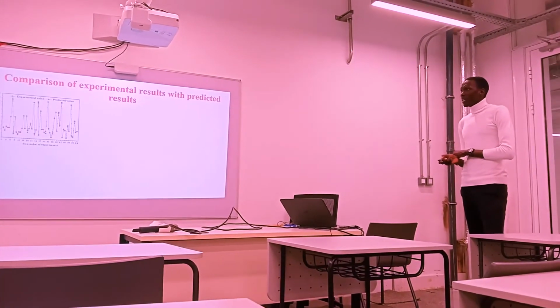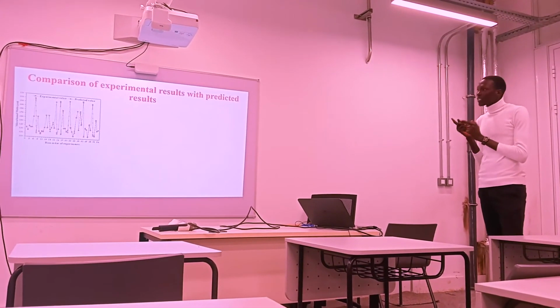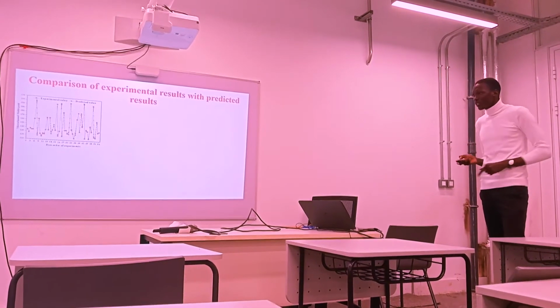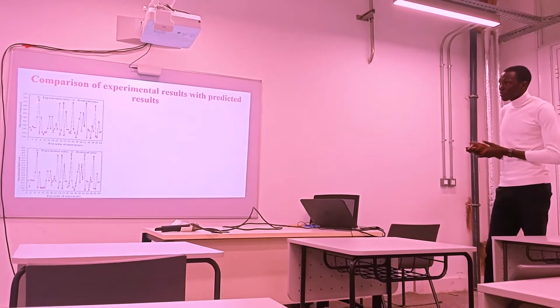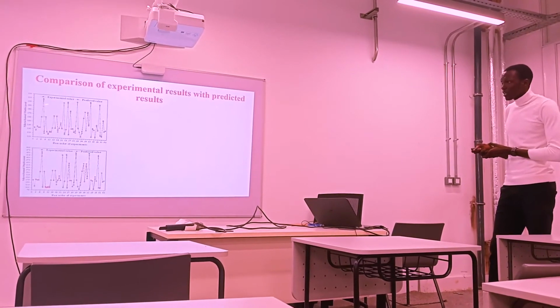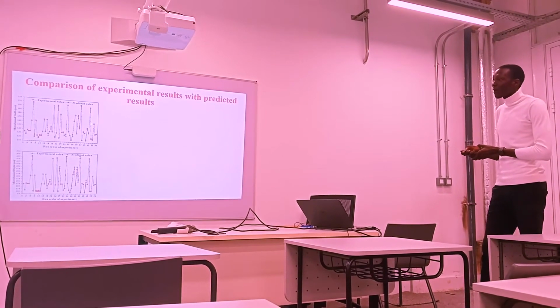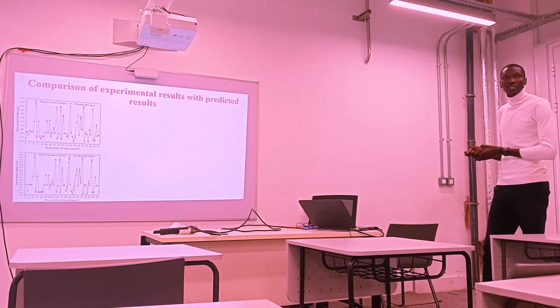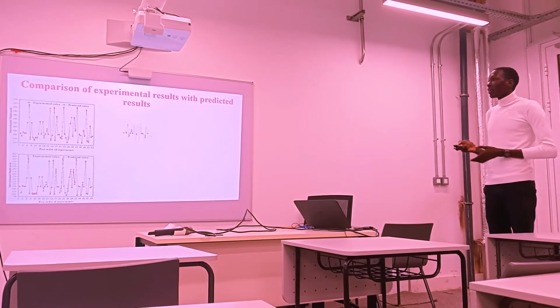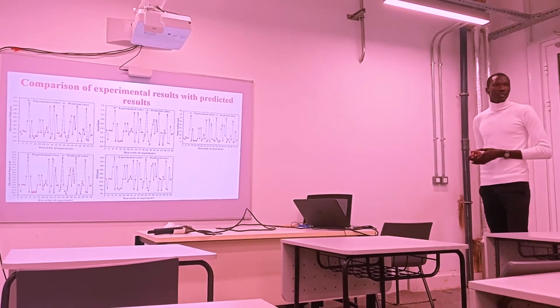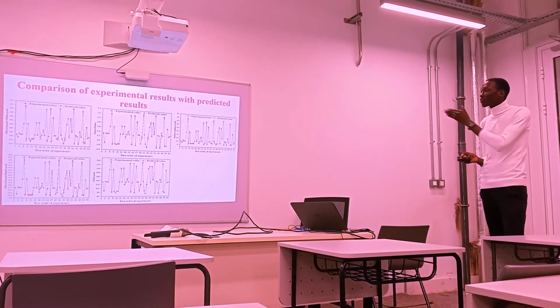Now, we compared the experimental results with the predicted results using those equations. And this is what we got for the width. The black line represents the experimental values, and the red line represents the predicted values. As we can see, in all the graphs, the experimental values are close to the predicted values.